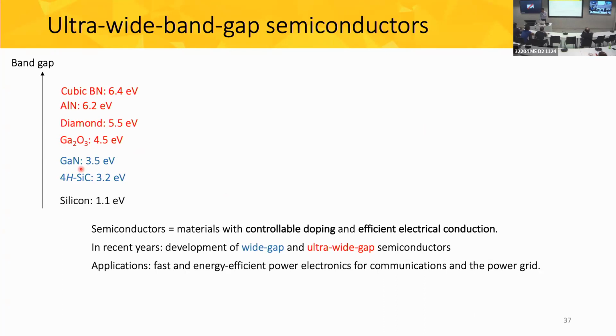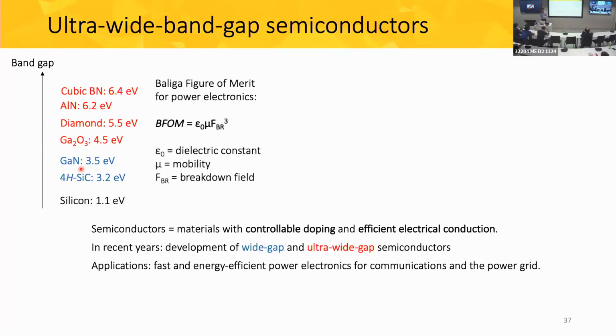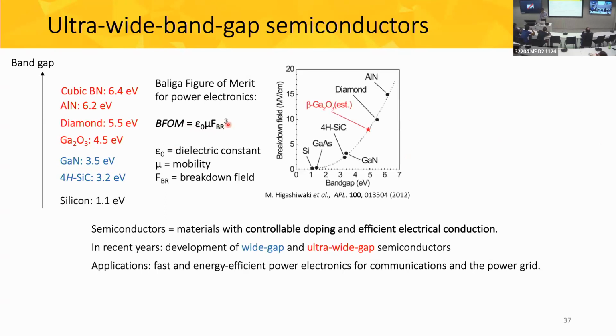Now, you may ask why we want the bandgaps to be wide. The reason is that the Baliga figure of merit of power electronics helps us quantify this effect. The Baliga figure of merit tells us how efficient the semiconductor is for power applications, and involves the dielectric constant of the material, the mobility, and the breakdown field to the third power. The bandgap is important because the wider the bandgap, the higher the breakdown field in a superlinear fashion.